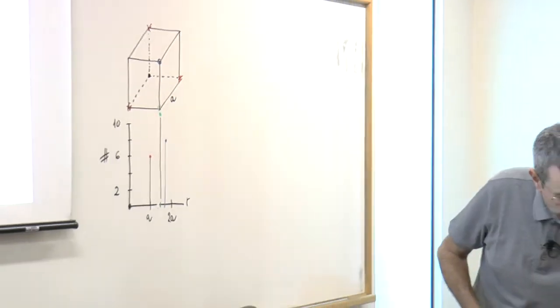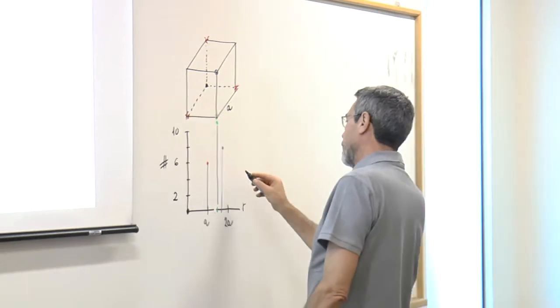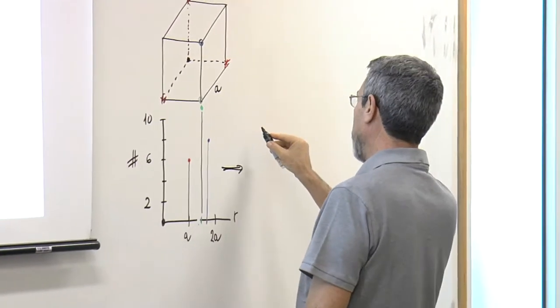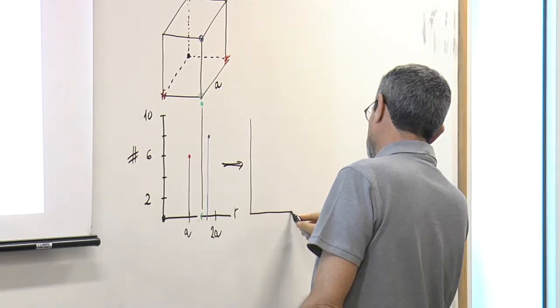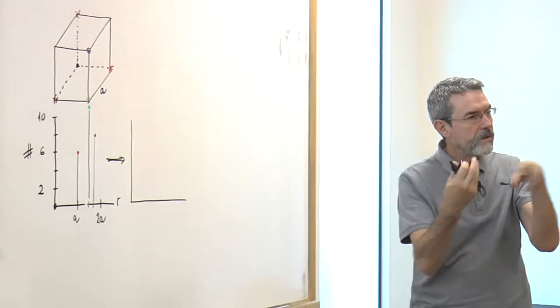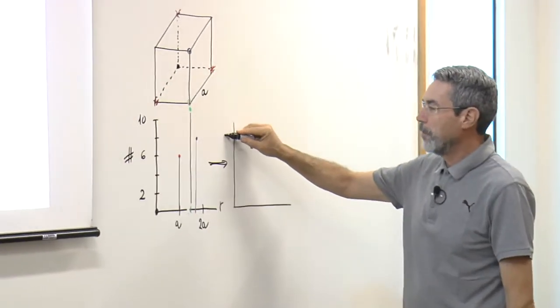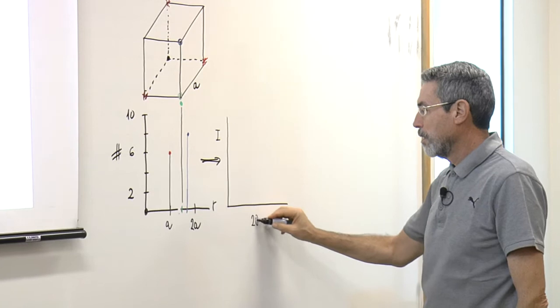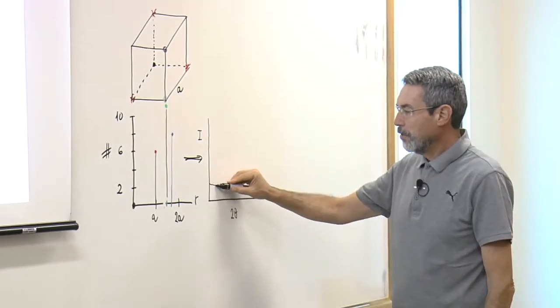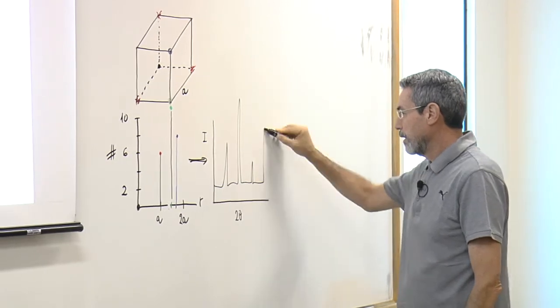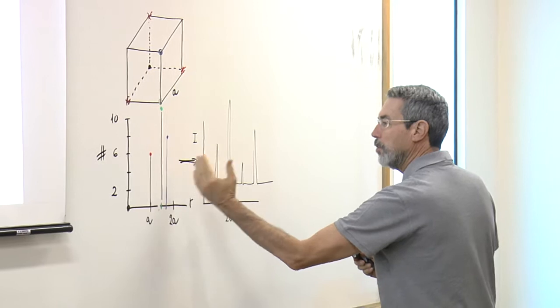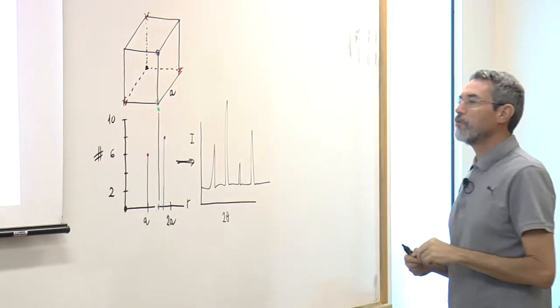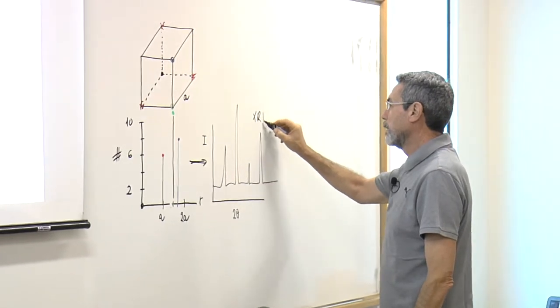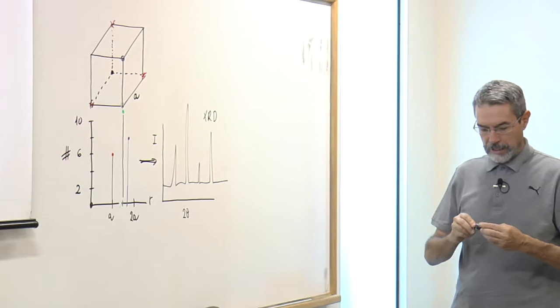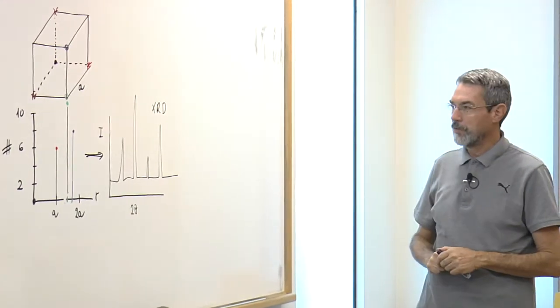Now, the nice thing about this is that when we do an X-ray diffraction, if we had a lot of these cubic crystals in a powder, with zillions of these cubic crystals, and we do an X-ray diffraction experiment, so the intensity versus the diffraction angle, you normally get a diffraction spectrum. This, of course, would continue. And this is the X-ray diffraction spectrum of a powder containing any of these crystals.